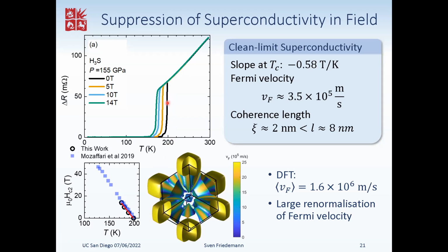So we do see the transition shifting in magnetic field as you expect for a superconductor. This shift of the critical field versus temperature is in agreement with work from the Eremets group. One should note that these are samples synthesized in different ways, namely our sample from ammonia borane, whereas Eremets' samples were synthesized from sulfur and molecular hydrogen. As a consequence, the resistance ratio of our sample and Eremets' sample is a little bit different, a factor of 2. But nevertheless, we see pretty much the same HC2 curves. That suggests that we are independent of the purity of the sample, meaning we are in the clean limit.